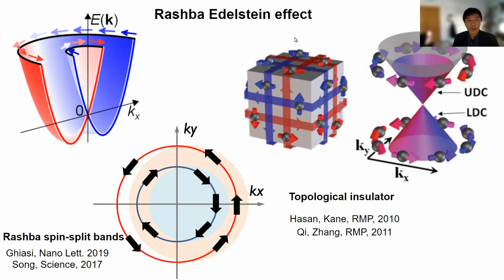So the Rashba-Edelstein effect refers to a non-equilibrium spin polarization that arises in materials which have a well-defined spin texture. This was first discovered in Rashba-like materials, which have the Fermi surface shown here. And you can see that every electron with a given momentum has a very well-defined spin-momentum locking. The momentum and the spin orientation are always 90 degrees apart.